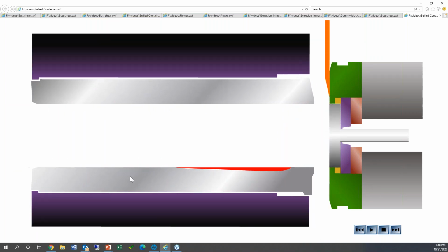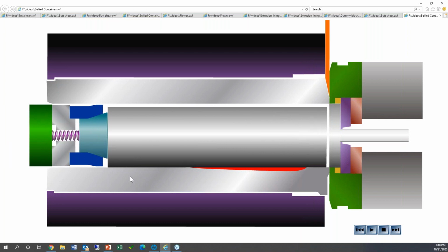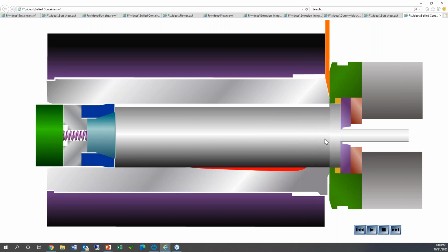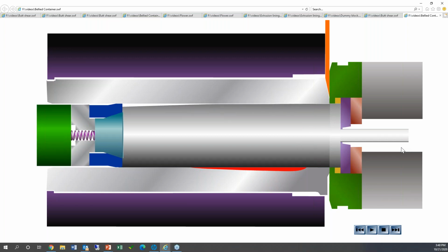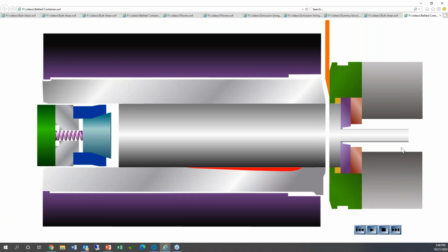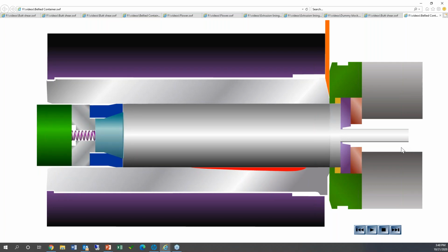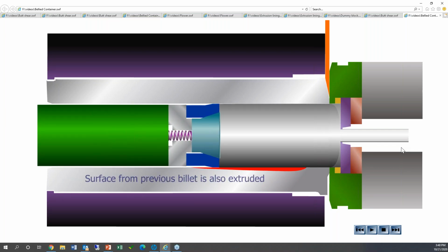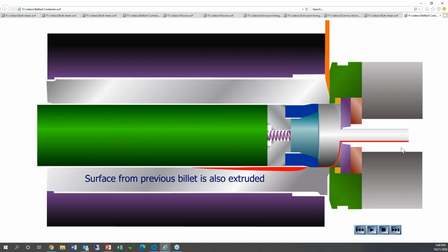After 4 to 7 billets, 4 to 8 billets of this, we start to see that inverse segregation zone that was on the billet actually ends up going through the container, through the die, and ends up on the extrusion. Now, it doesn't all go through the extrusion. Parts of it will stay in the die. So that's why some people will call me up and say, hey, Dan, we've got a surface finish issue. Where is it? Well, it's front, middle, and back. Oh, no, it's just in the front. Oh, well, no, maybe it's just in the back. Well, it's intermittent. It could either be type 1 inflow, which any of that billet skin that gets into the die is going to park there. And it's going to come out whenever it feels like it wants to.